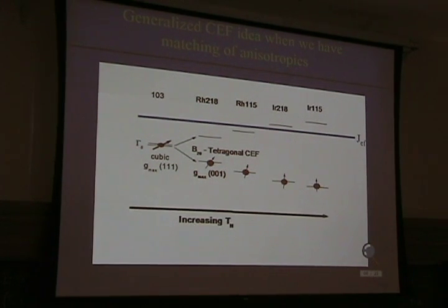That new parameter can compete in terms of anisotropy with the cubic ones and can change the direction of your moment to a direction that gives you a better matching of anisotropy between the parameters, and it increases the Néel temperature. So somehow, when you go to the lower symmetry and include that parameter, you are having a better matching of anisotropies along the different parameters. So it kind of releases magnetic frustration and increases the Néel temperature.